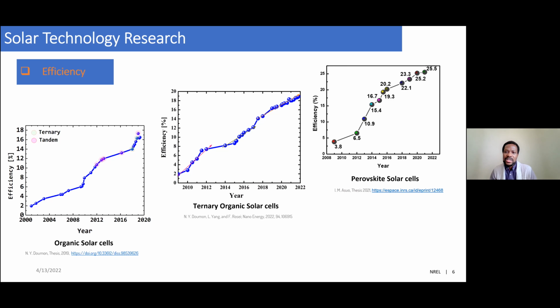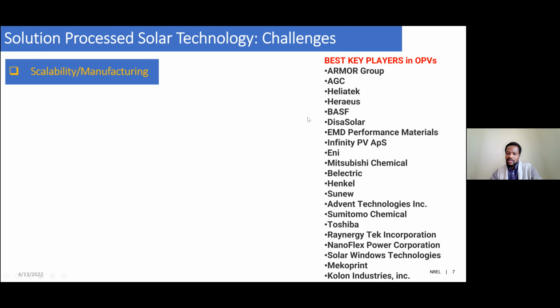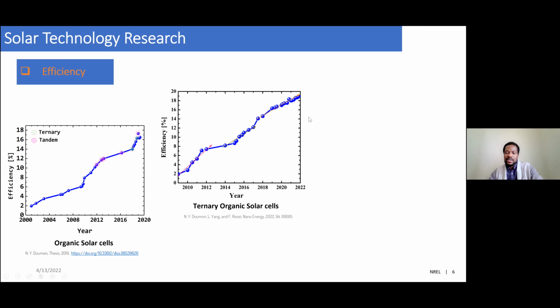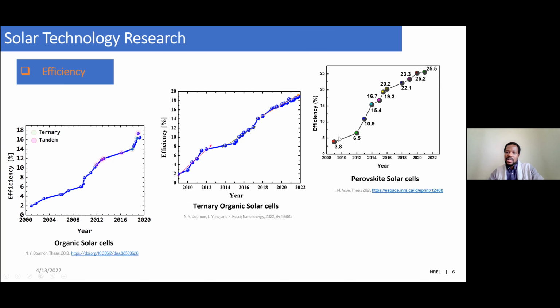And you can see that this trend, if you draw a straight line, has a very high slope. While this is a good development for the community, it was bad news for the photovoltaic field, the OPV field, because most of the attention was shifted from the organics to the perovskite. But thanks to the advent of the non-fullerene acceptors, the OPV field is still alive today.